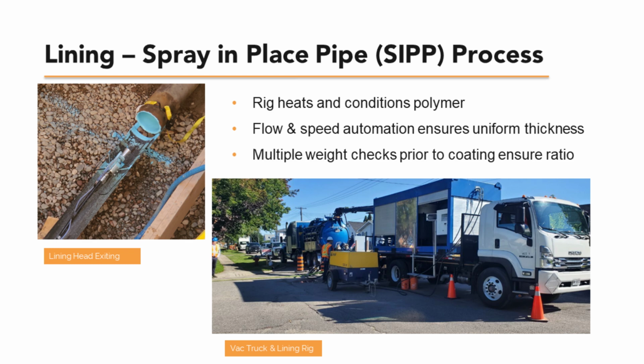The lining rig heats and shears the polymer to maintain optimal properties. Automation of feed rate and winch speed, again, ensure uniform thickness, and weight checks are done prior to coating to ensure proper mix ratios. Flow meters monitor mix ratio throughout the lining process, and the overall lining process is subject to an NSF approval.